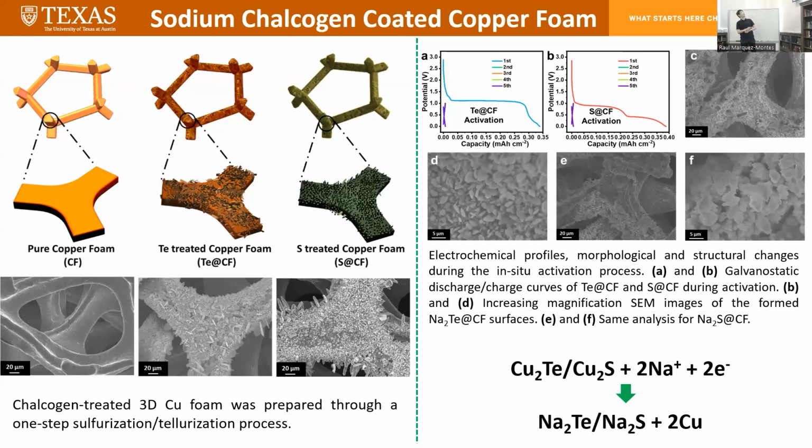However, during your first charge, you see here, it doesn't give you any capacity, which again proves our hypothesis that this material does not undergo reversible alloy and de-alloy reactions. Also, in the subsequent cycles, almost zero capacity can be extracted, which again proves that those materials are stable at the anode side, given a potential window up to 1 volt.